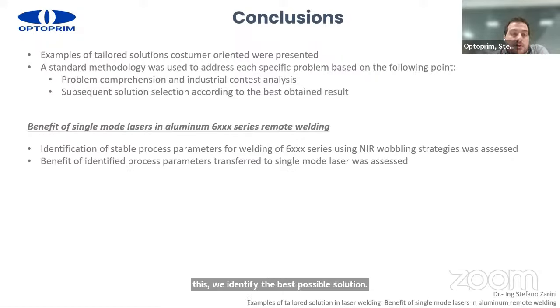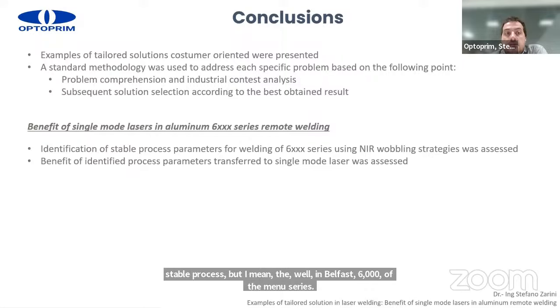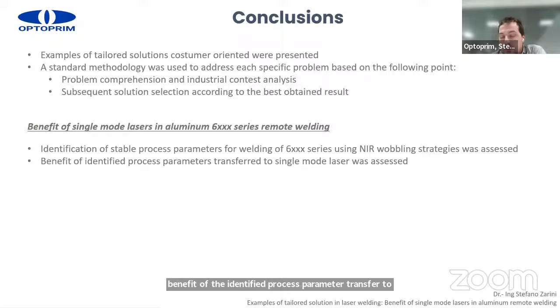We went quite straightforwardly to an example case that we presented, but we could have had many more, and this is our daily routine. An identification of stable process parameters for welding of 6000 series aluminum using a near-infrared wobbling strategy was assessed, and the benefit of transferring the identified process parameters to a single mode laser was assessed as well.